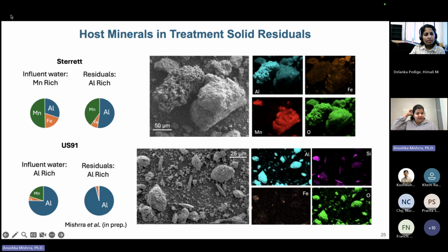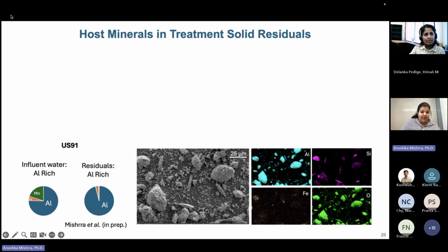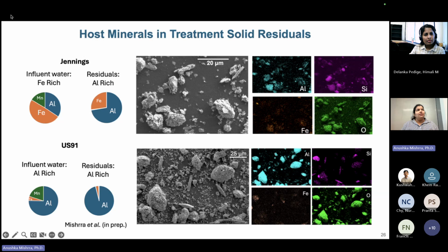There were also some diatoms that I could see under the microscope. So it's interesting how we now don't have enrichment of manganese in it, but we have more enrichment of aluminum, silica, iron, and definitely oxygen all over the treatment solids. There is one other site that I would like to also compare with US91, which is Jennings. The reason I bring this up is for the same reasons, that the residues are very rich in aluminum, but the influent is now rich in iron. So if you had a very iron-enriched fluid, do you see iron precipitating out in the treatment solids? The answer is partly. I don't think all of the iron ends up precipitating in the solids.